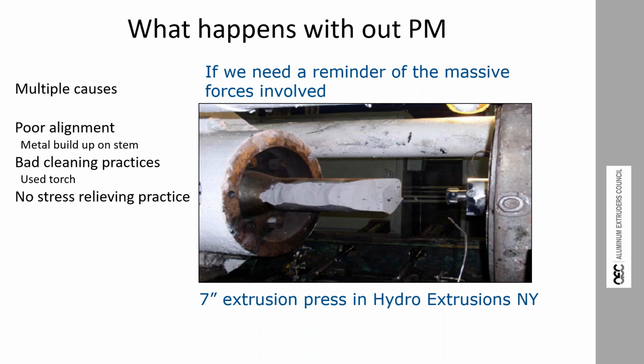We found the root causes were poor alignment. Metal had built up on the side of the stem, and they knew it wasn't right, but they'd let it tolerate it. They'd lived with it. In fact, you can see on the edge of the dummy block here some of the metal building up. They wanted to get rid of this in a hurry because they had visitors coming from head office. So someone took a torch and tried to get the aluminum off, kind of get it hot and scrape it off so it didn't look so crappy.